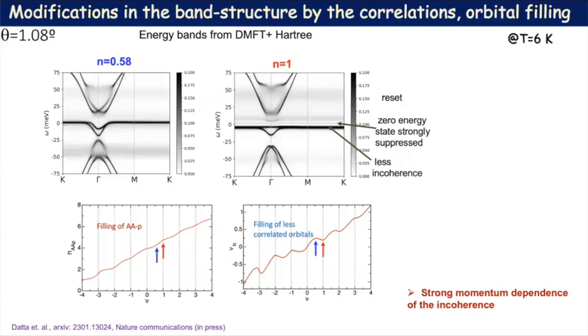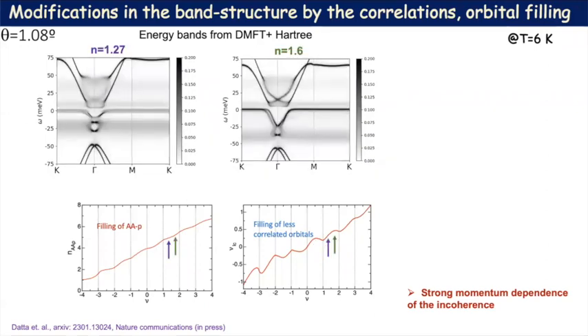So now the filling starts to happen in these orbitals, and you can see that there is an increase in the filling of AP orbitals, and there is actually a decrease in the filling of the less correlated orbitals. This decrease is mainly because the less correlated orbitals are coupled to these strongly correlated AP orbitals, and so it is energetically advantageous to lose some of the electrons in the less correlated orbitals. This continues until filling factor 1, where we have a reset. And then beyond 1, we again have the same picture.